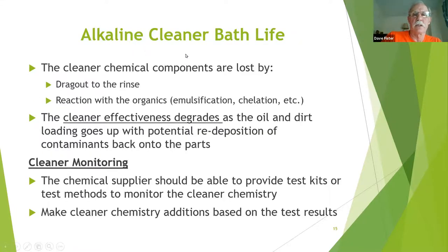Okay, back to alkaline cleaners. The first step in removing dirts, oils, greases from parts before you get to the next step. At least my experience has been, I would say, every place I've been to has used alkaline or caustic cleaners in their first bath to take off the oils and greases. So again, cleaning chemistry is lost, drag out to the rinse, reaction with organics, emulsification, chelation, etc. And as the cleaner effectiveness degrades, you have that potential of redeposition of contaminants back on the parts, which then suggests you're going to be doing some rework.